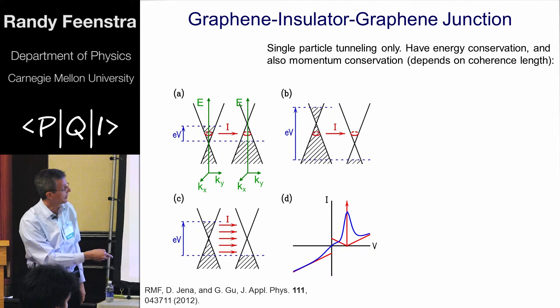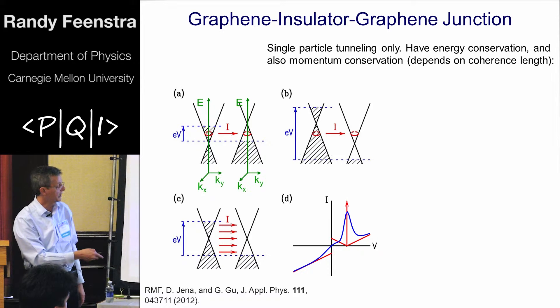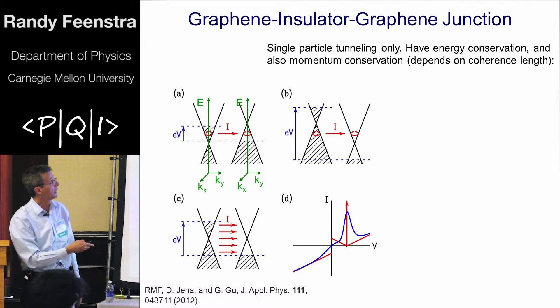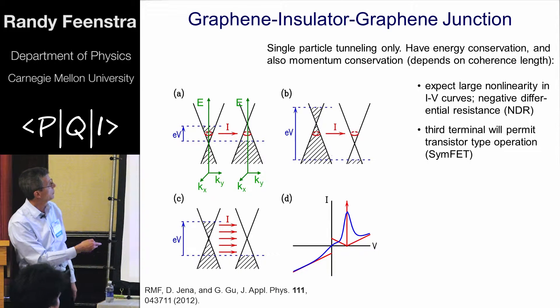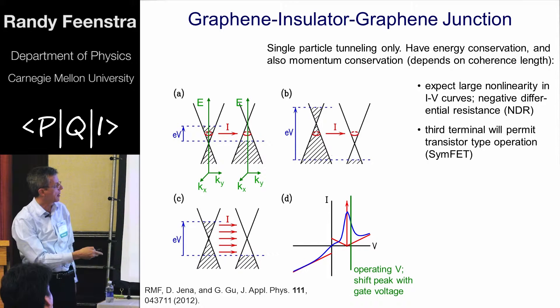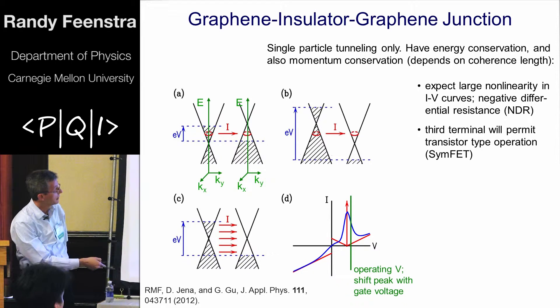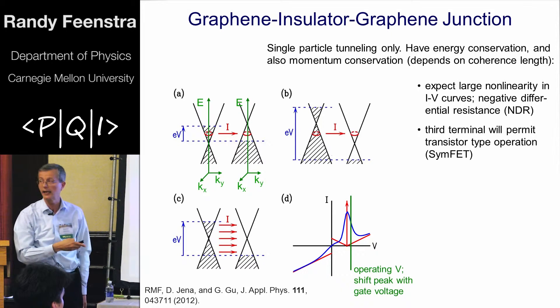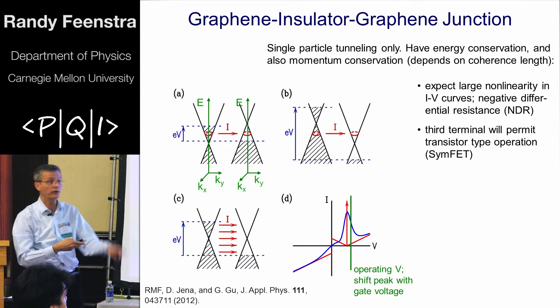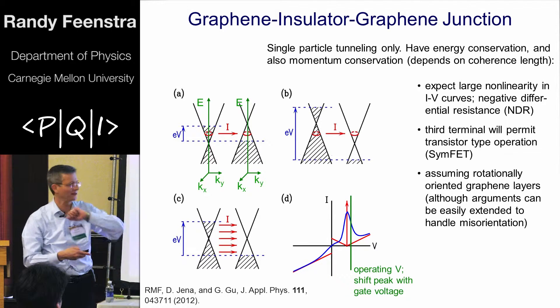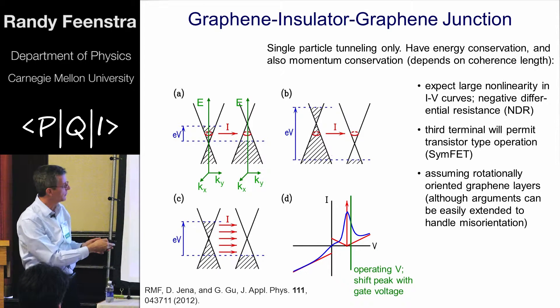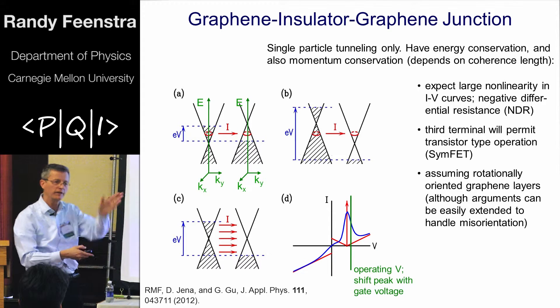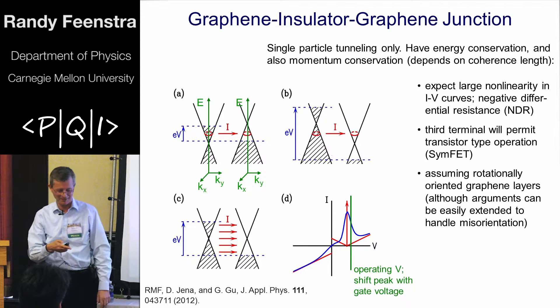The prediction is a very sharp and large peak in the IV curve. This immediately has device applications: you put an additional gate electrode on top and bottom, shift the gate voltage, sweep this peak back and forth, measure the current — that is a transistor. This assumes rotational orientation to address the question raised. In graphene we can tolerate a few degrees of misorientation — the peak will shift around — but if misorientation is larger than that, the peak will go away.